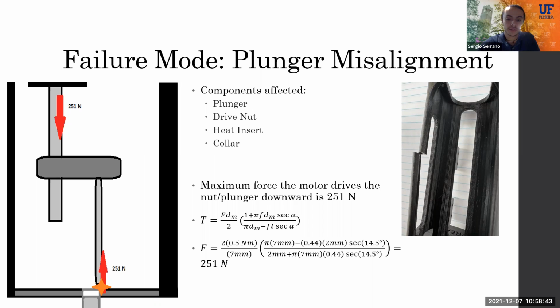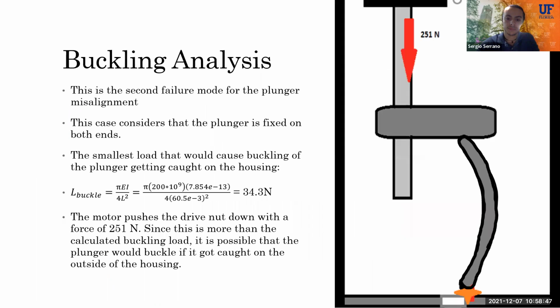And a picture of that is shown on the right. The equation for buckling of a column was used to determine if the plunger would buckle under this failure mode. It's noted that the plunger is fixed on both ends in this failure situation. So the equation for buckling of a column with two fixed ends is used, and the length of the plunger was taken from the face of the drive nut to the end of the plunger.